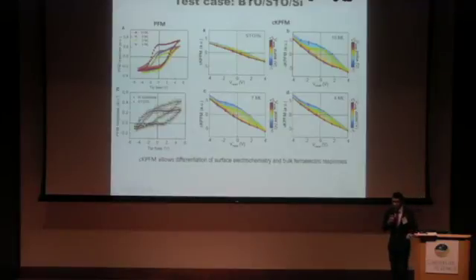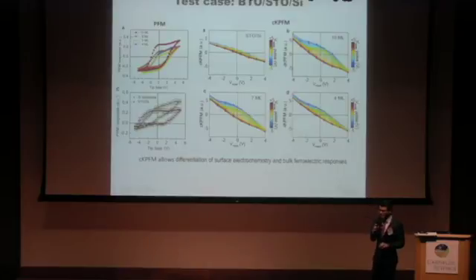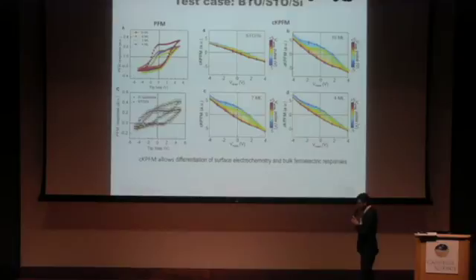So that's a really good question, and we've written a very long review article on that topic, so I'm happy to send it to you. It was very painful. But basically, what I'm willing to say here is that we know what a true ferroelectric looks like in the CKPFM experiment. So when I say true ferroelectric, when the polarization is very large, so PZT, barium titanate, lithium niobate, we can see a clear dispersion. So we can clearly see the distinction between this type of CKPFM result and what we got in the STO. On a more fundamental level, I cannot claim that just because it does not show this type of behavior in this experiment that material is not ferroelectric.